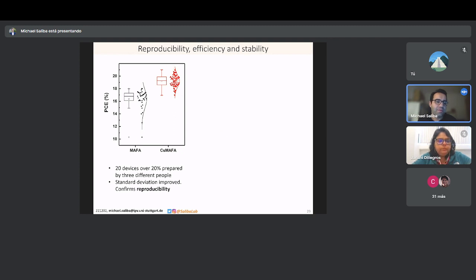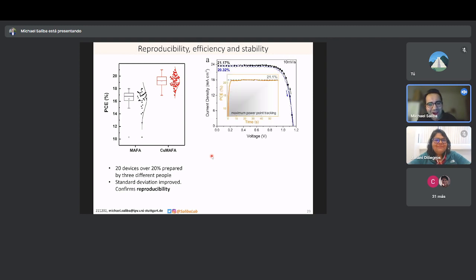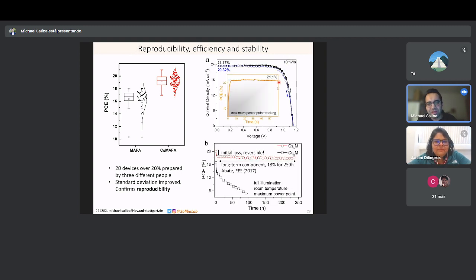And it was very interesting because at the time, one of the reviewers also asked us to demonstrate by more than one person. So we put another 2 people on it, and they could indeed show that they can also reach 20% now as well, confirming, I think, very nicely our reproducibility. So we're very, very grateful to the reviewer, although it didn't feel like that at the moment. And here you see also a stabilized power output of 21.1% with very little to no hysteresis. We also saw long-term stability for 250 hours at 18%.